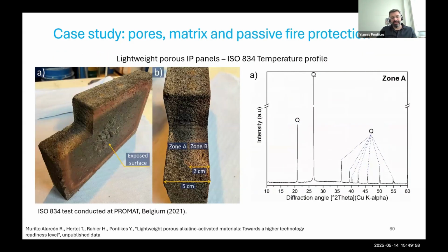The formulations that do not have this cement hydration products can also be more fire resistant, and that has been a big thing in the group. Where would you use that? Typical application would be in a tunnel. So you try to protect the concrete, so you put a whole layer of these bricks to protect the concrete in the back. But anything that is exposed at high temperatures or a flame can actually be interesting for these bricks. You have then different tests. They go to different temperatures. Here is the ISO test, but you can go up to, I think, 1340. And yeah, you typically have the flame on one side, and then you see the performance on the back.